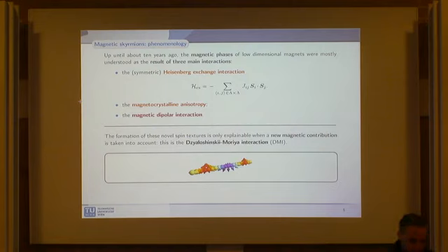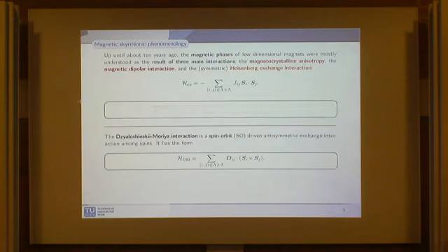And if you take some special ferromagnetic material, you consider these layers, he was observing that the main configuration, so the global minimizer, is something like a helicoid. And so he proposed that the fact that you can see this kind of helicoid is due to the fact that there is another kind of interaction which is anti-symmetric, which nowadays is called the Dzyaloshinskii-Moriya interaction, and which